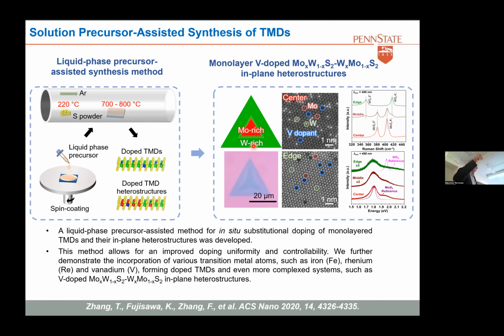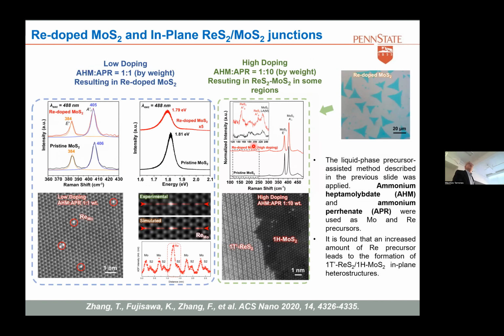But we are finding even more interesting shapes that I can show you. So for example, we did some work with rhenium, right? In the case of rhenium, we use the precursor of rhenium. So this case is moly sulfide, right? We use ammonium heptamolybdate, that's the moly precursor, and the ammonium perrhenate, that's the rhenium precursor.